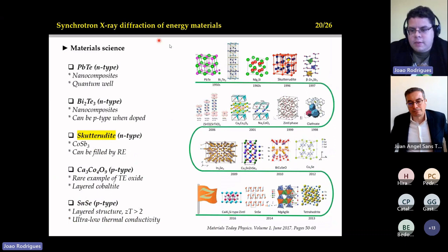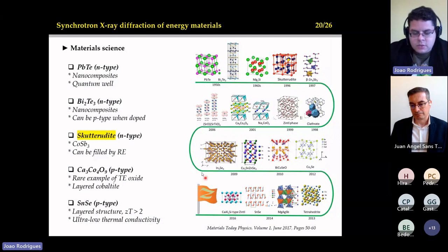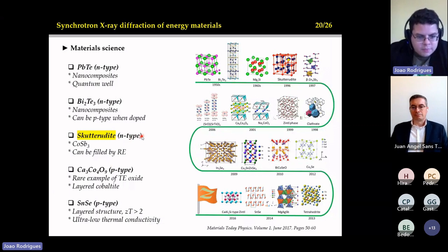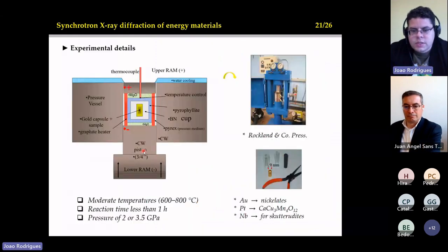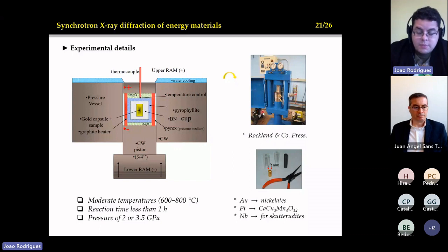So these are a track of all the materials that they have investigated up to now. The most interesting thing is this skutterudite, because it's an n-type material. You can fill this material with rare earths. And the main advantage of this one is the low thermal conductivity. In a thermoelectric material, we need to optimize three parameters, which are the Seebeck coefficient, the electrical conductivity, and the thermal conductivity.